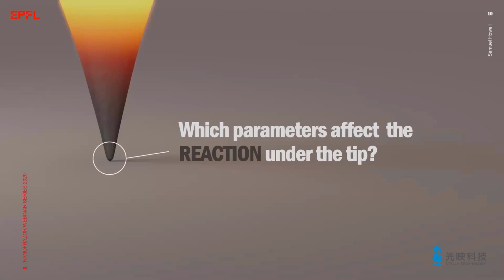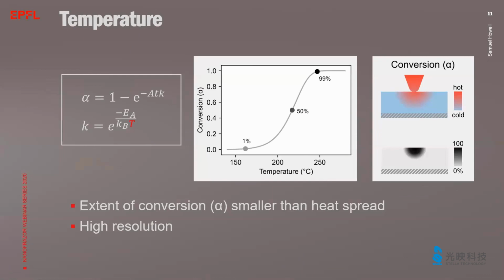The next question is, what happens when the material under the tip is heated to a certain temperature? I mean, we want to trigger a reaction or a change in the material. Therefore, let's look at the main parameters that affect such reactions. The most important parameter is the temperature. For example, for a simple thermal degradation reaction, the kinetics can be described by a first-order rate equation, as shown in the slide. The relative amount of converted material, alpha, can be expressed as a double exponential function with respect to the temperature. The conversion function or the reaction function is plotted as a function of the temperature. The circles here indicate 1%, 50%, and 99% completion of the reaction.